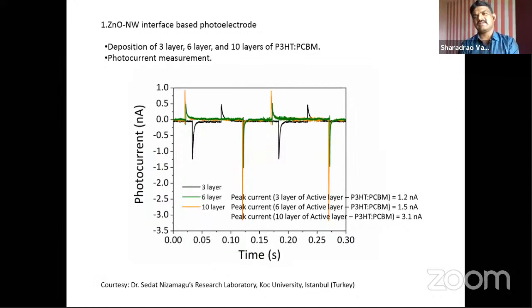It consists of a substrate on which we deposited zinc oxide nanorods, on which we deposited P3HT, followed by the PCBM layer. This three-layer assembly we call the active layer. When we tested this active layer for photocurrent, it gave a good current, about 1.2 nanoampere to 3.1 nanoampere. Deposition of 3, 6 and 10 layers of P3HT PCBM over the zinc oxide nanorods shows good efficiency.